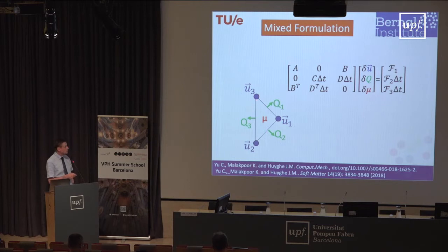If you take now the example of a triangular element, you have the displacements unknown in the corners and three fluxes. On top of that, we have one pressure, or in case of swelling, it is a chemical potential in the middle. And we can write down the full equations as we have them from the equations I just showed you: conservation of momentum, conservation of mass, and Darcy's law. And we can solve those equations, but as you see, we have more degrees of freedom than if we had taken pressure simply, because we have those fluxes.